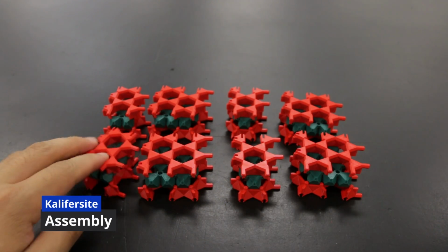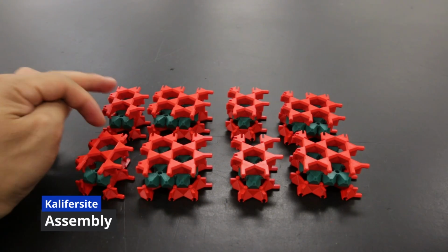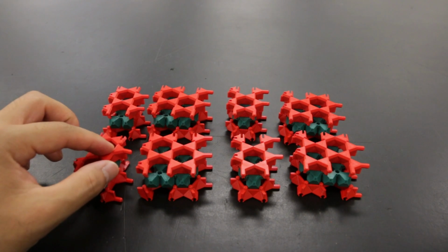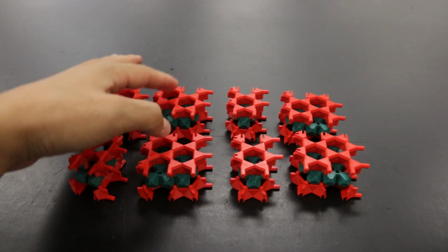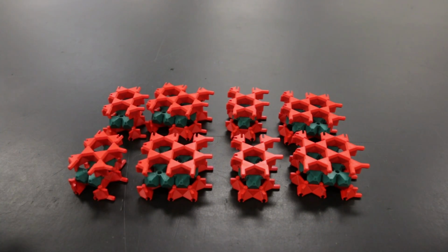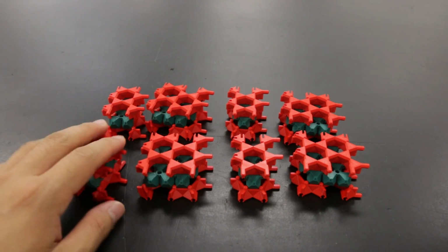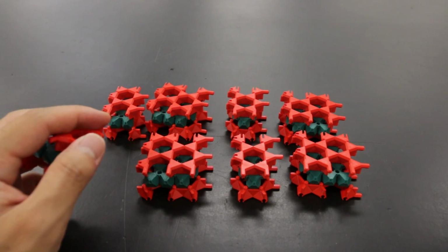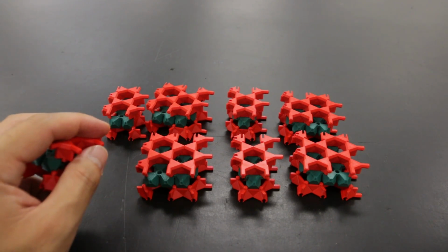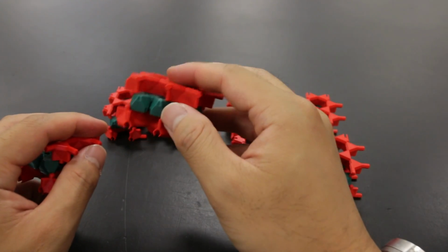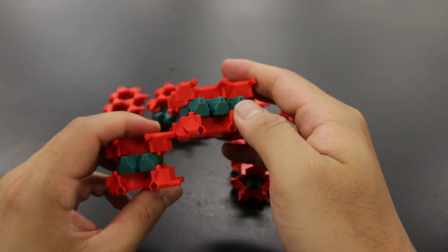To construct the Kalifersite structure, 2 double chain width TOT modules, which are constructed using Z3O+ modules, and 2 triple chain width TOT modules, which are constructed using Z6O+ modules, are needed. So the T- of 1 double chain width module is connected to the T+ of a triple chain width module.